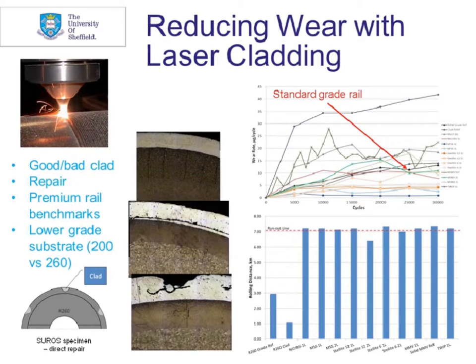The graph with the blue bars is showing the rolling distance required to create some rolling contact fatigue type damage. Now, in fact, most of the materials ran out, so in that sense, we didn't actually create any cracks in them. They're very hard to deform. You need that kind of deformation process started to initiate and grow cracks. So a lot of these clad materials are promising in terms of reducing wear and rolling contact fatigue.